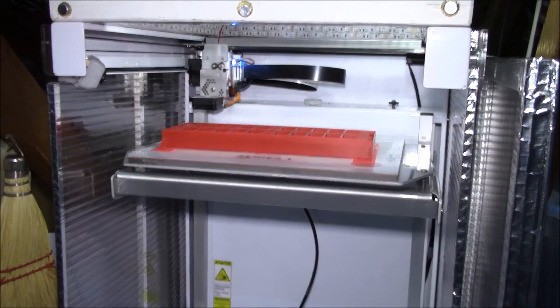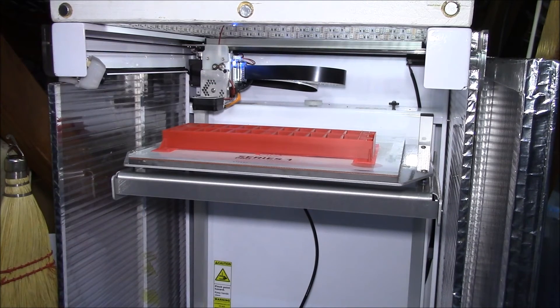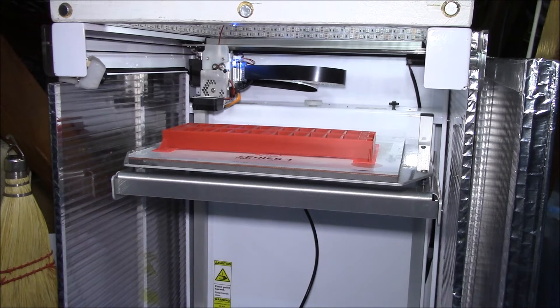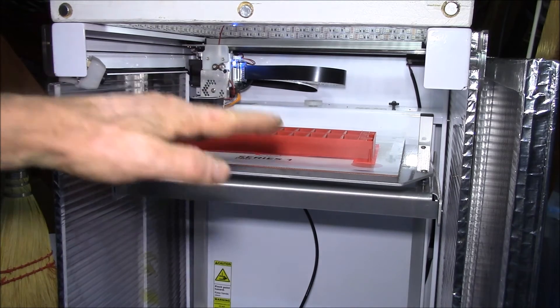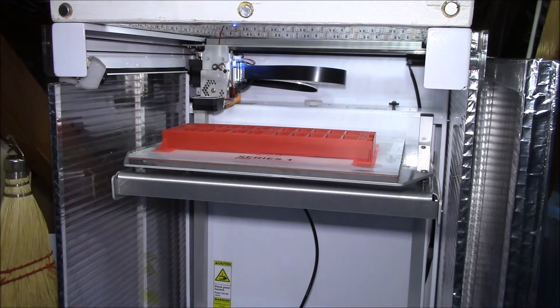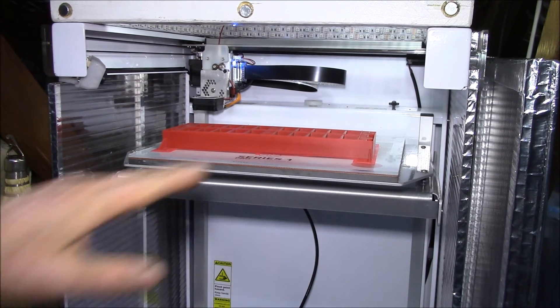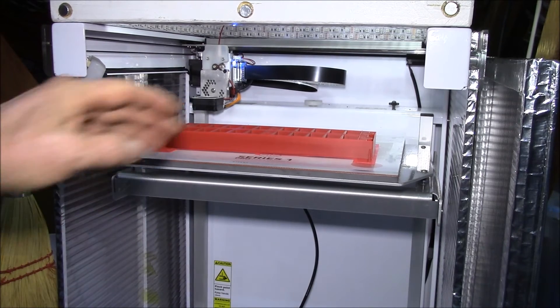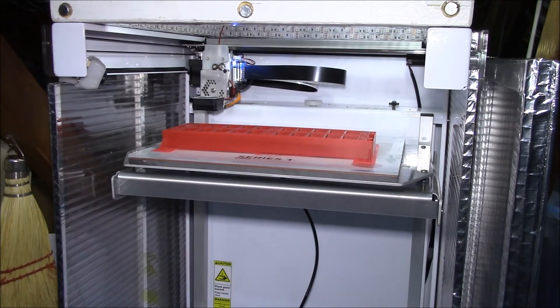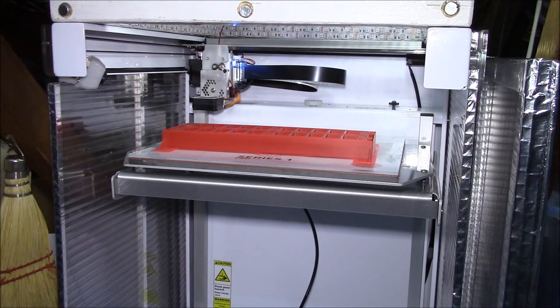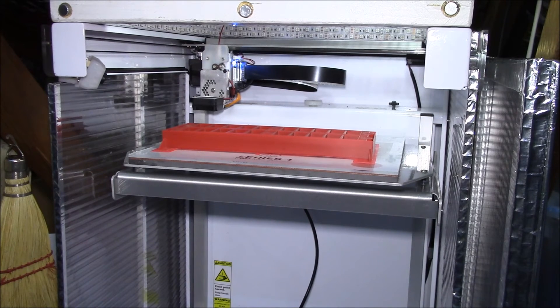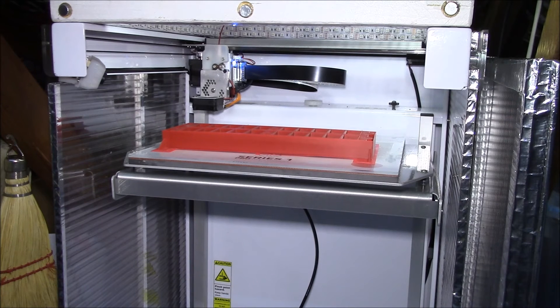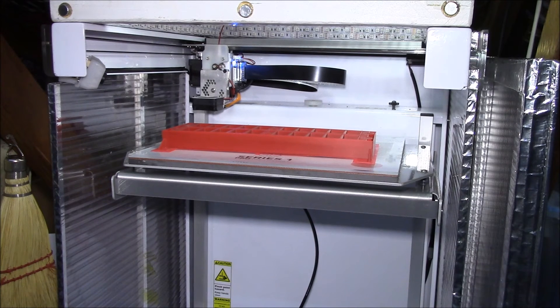What I did: I used the Cura plugin called Tweak At Z, which is a little plugin you can enable. Then you tell it at a certain print height or Z value you can change a parameter. So what I did was I set it at two millimeters. I changed the bed temperature from 115 down to 100 and that worked. I watched the end of the print finish at 100 degrees C. The beginning was 115. So that plugin seems to work.